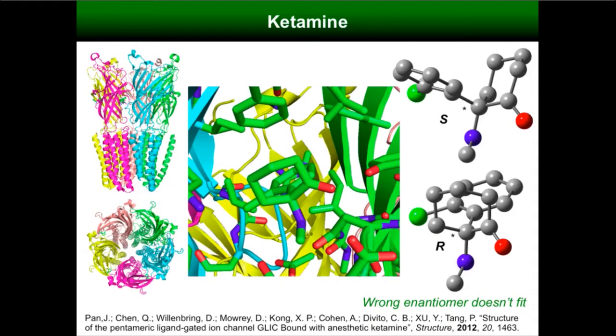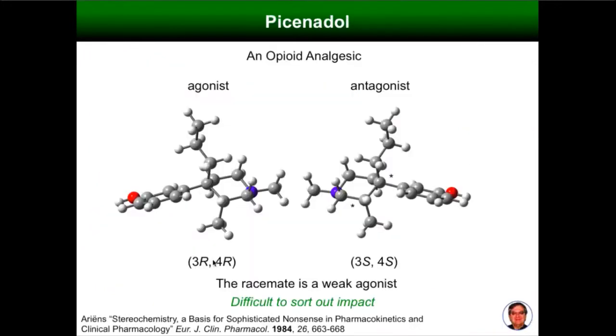If you look at the active site for ketamine bound into an ion channel called GLIC, this is one of the enantiomers in the active site. You can see stabilizing interactions, and it turns out this is the R enantiomer of ketamine in this active site. The other glove, the other hand, doesn't fit. The shape actually makes a difference. Another drug, an opioid analgesic: one enantiomer is an agonist, the other an antagonist. The racemate is a weak agonist. So sorting out the impact requires being able to control the stereochemistry.